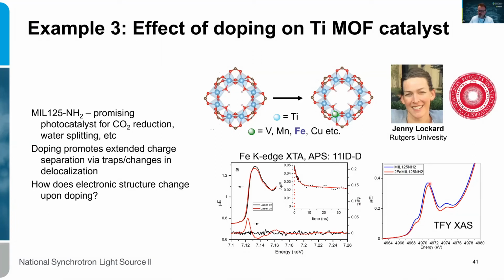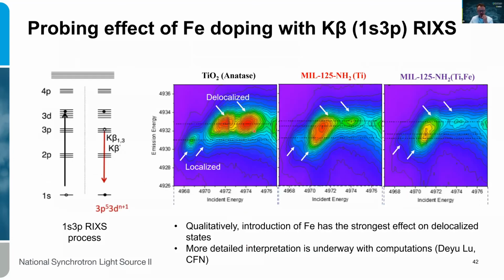However, the molecular level understanding of what is going on is not there yet. So again, we can compare just the regular XES. You see there's very little difference between the undoped and the doped material. But once you resolve the same spectra in two dimensions, you start seeing features that are quite different between the native material and the doped one, especially in the region that's associated with the delocalized states in titanium. And again, we have to bring theoreticians on board to get a better understanding of what we're actually seeing here. All right, so much for science.